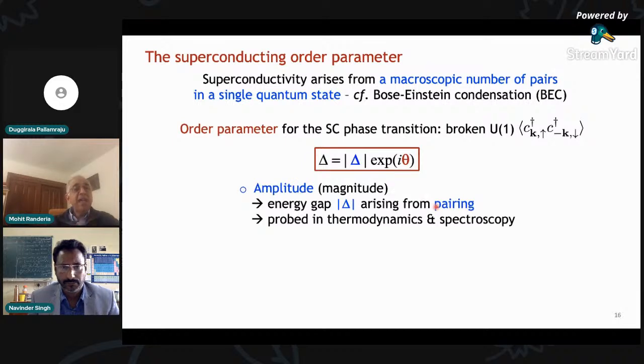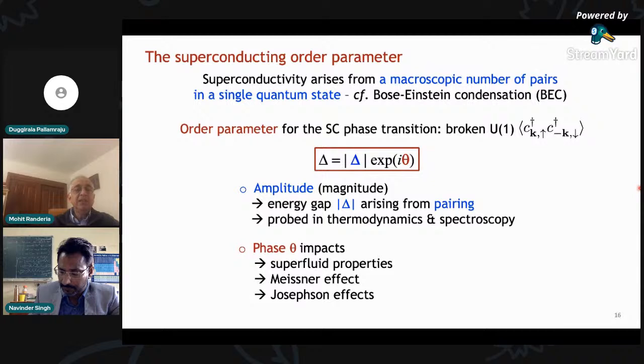The amplitude is the magnitude of the order parameter, and actually, when written in correct units, it's just the energy gap that arises from pairing. And this leads to all the experimental things that you can probe in thermodynamics and spectroscopy, telling you that there's an energy gap. But there is also the phase, which is often not talked about in elementary classes. But in fact, it is the phase which is responsible for all the superfluid properties: motion of charge without dissipation, expulsion of the magnetic field, and the Josephson effect.